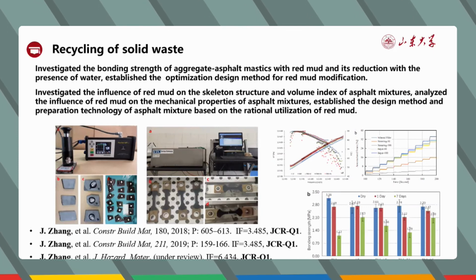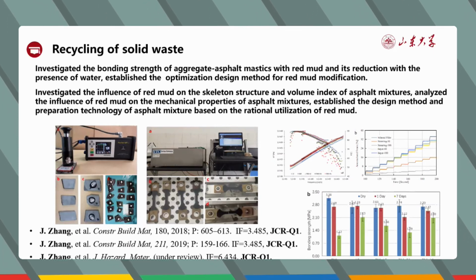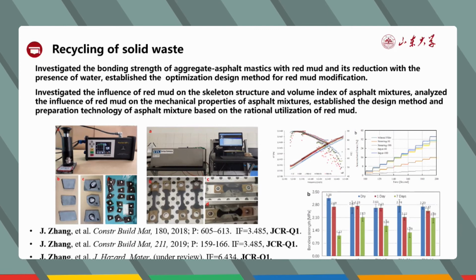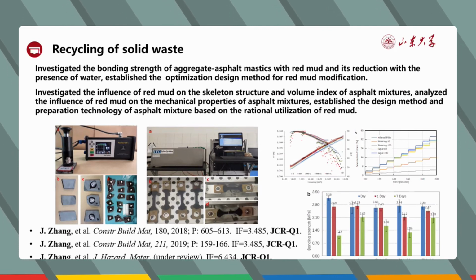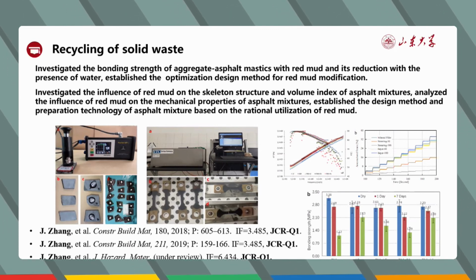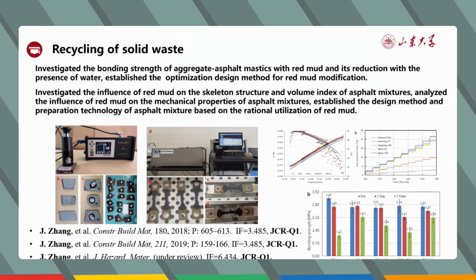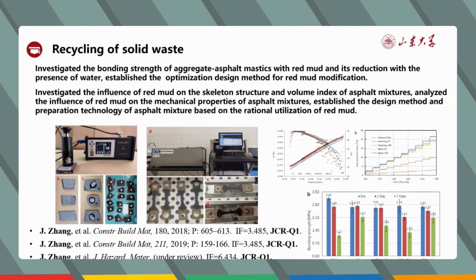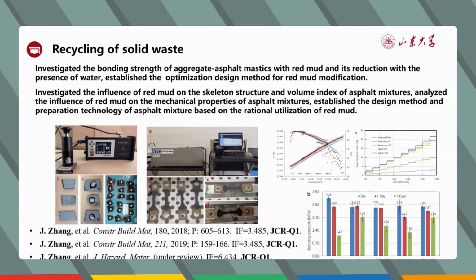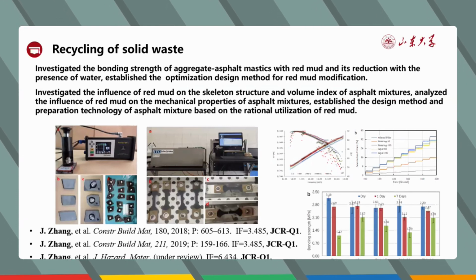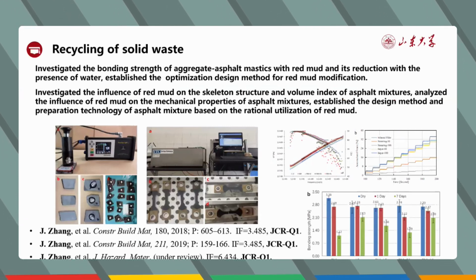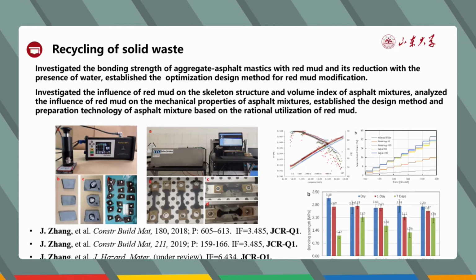We also investigated the influence of red mud on the skeleton structure and the volume indices of asphalt mixtures, analyzed the influence of red mud on the mechanical properties of asphalt mixture, and established the design method and the preparation technology for asphalt mixtures based on the rational utilization of red mud.